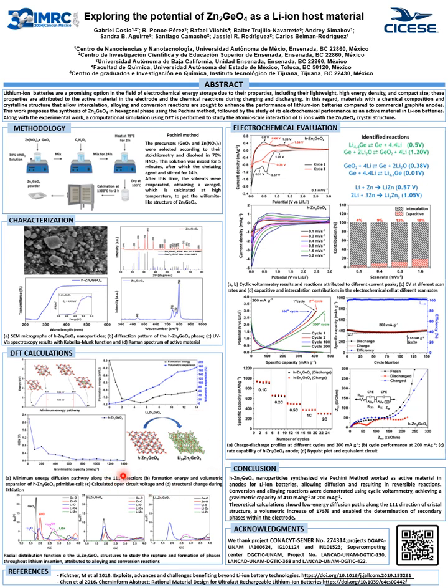The formation energies and volumetric expansion for each inserted ion were calculated, demonstrating thermodynamic stability during lithium insertion with a maximum volumetric expansion of 175%. The open circuit voltage was also calculated, showing a profile similar to the charge and discharge curves, confirming the theoretical capacity of 410 mA per gram. The final image depicts the structural changes observed in the primitive cell of the material upon ion insertion, including a complete loss of symmetry and the apparent breaking of germanium oxide and zinc oxide bonds.